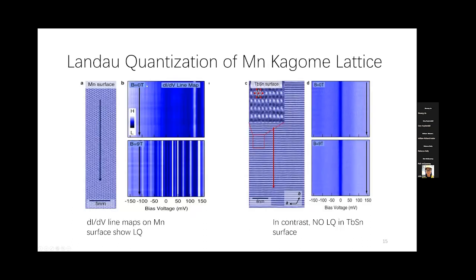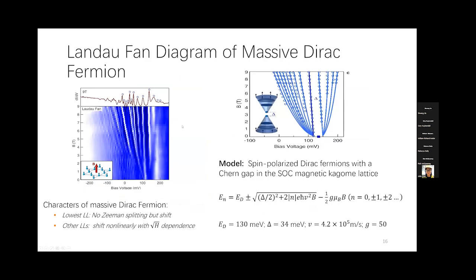So our collaborator, Professor Zahid Hasan at Princeton, his group did some STM spectral measurements on the surface of terbium 166. They did dI/dV measurements on the manganese surface, the kagome surface, and also the terbium tin surface. Basically, they detect a very clear massive Dirac fermion Landau fan diagram on the kagome lattice. And this fan diagram can be well described by a theoretical model which describes massive Dirac fermions with a Chern gap equal to 34 millielectronvolts and the Dirac point energy equal to 130 millielectronvolts.